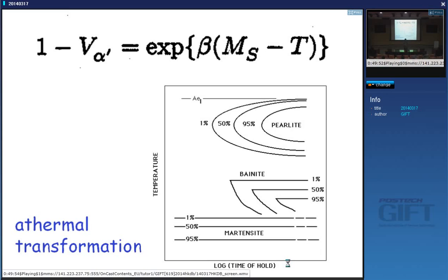And there's a nucleation stage and a growth stage for martensite. So if you could observe fast enough, you would see the plates actually growing. And with shape memory martensite, it's a slow transformation. It's diffusionless, but slow. And you can observe the plates growing and shrinking. And if you go to the online course, there's a movie there showing you the martensite forming and unforming. And there are at least 100 movies on my website to show you the martensitic transformation. Yeah, slow and fast.